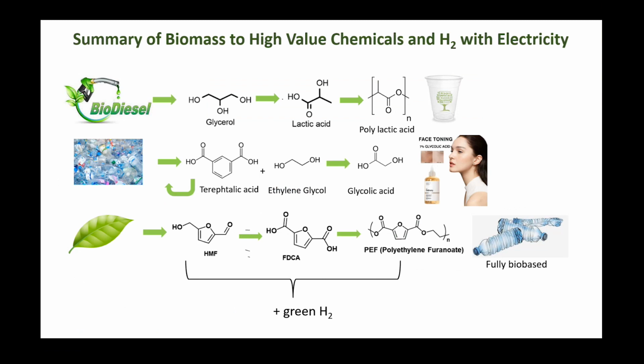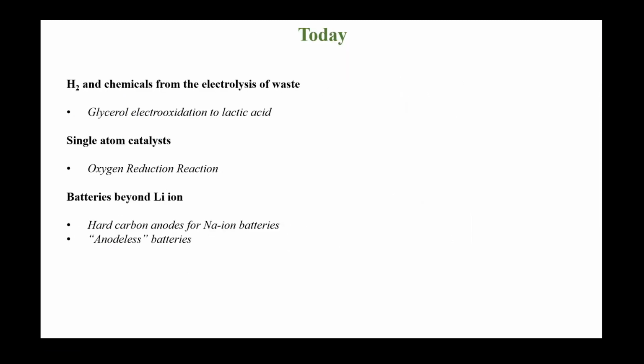And so this is something that we're doing. We are also working on other oxidation reactions from glycerol. In particular, one exciting development is trying to use PET directly, to depolymerize it through an electrochemical pathway to terephthalic acid and ethylene glycol, which are its monomers. And we can go one step further and convert this ethylene glycol to glycolic acid, which is a very nice cosmetic for your skin, and hydrogen. We are also working on oxidizing hydroxymethylfurfural to furandicarboxylic acid, which is a nice monomer for making polyethylene furanoate, which is a bio-based version of PET. And in all these electrooxidations, we are aiming to maximize current density and selectivity and produce green hydrogen on the side as well.